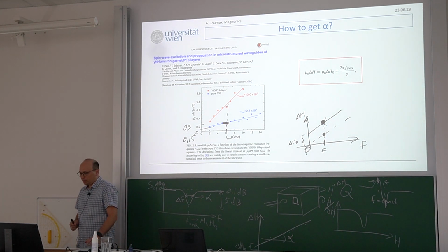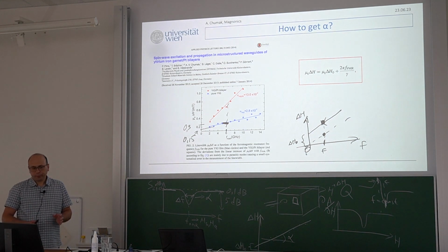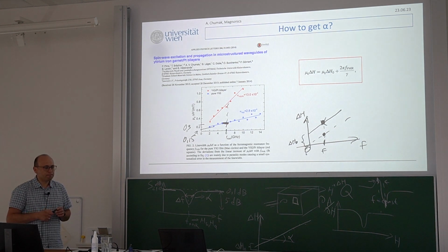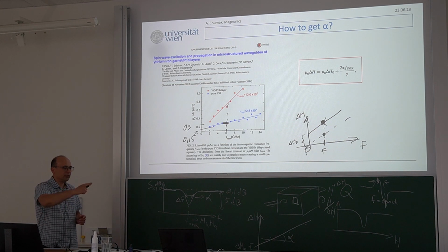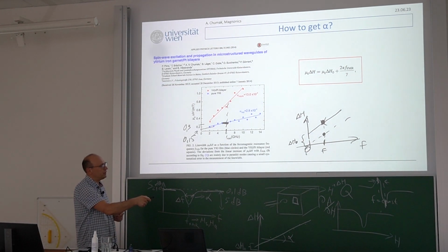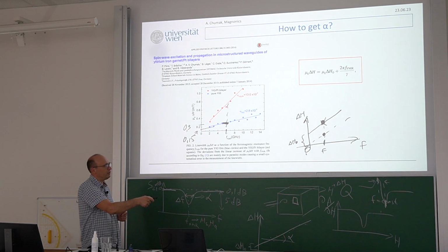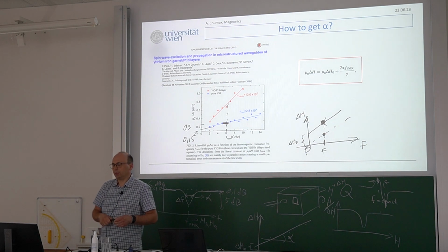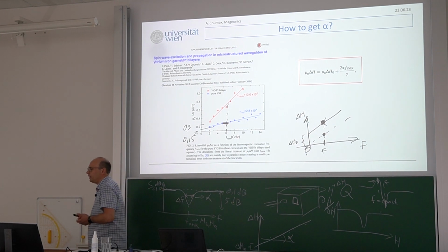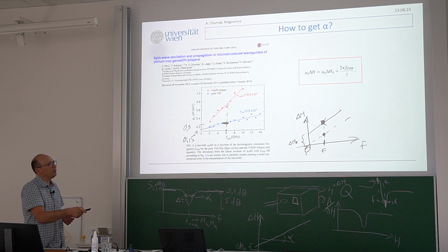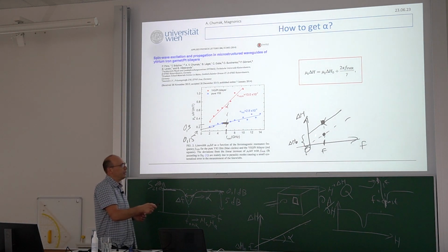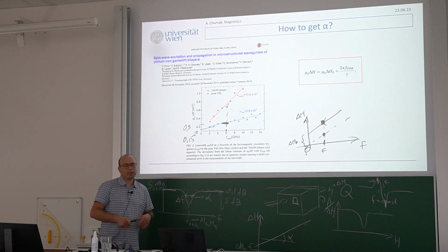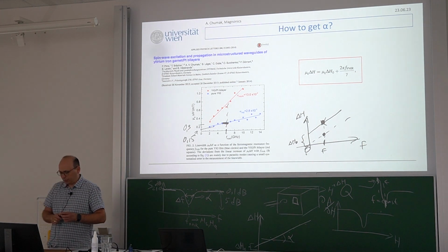Why is the delta H0 critical? What is the physical meaning? The smaller the precession frequency you have, the smaller the damping is. And if you have no precession frequency, F resonance equal to 0, in principle there should be no damping. So theoretically, this line, delta H versus frequency, should go to 0. In practice, it's practically never the case. There will always be some offset, and we need to take it into account.